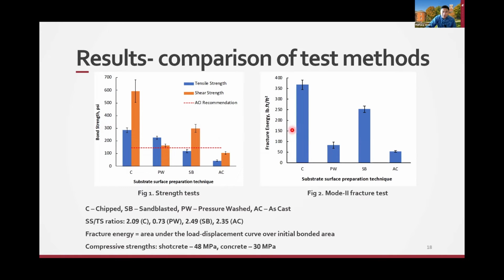In terms of the butterfly test method, which measures the fracture energy, because you do place the notch before the test, it follows the pattern of the shear. As you see, the chipped method surface preparation gives you the highest fracture energy, followed by sandblasting, then pressure washing, and as cast. So it seems mode 2, which is also a shear test, makes sense. It follows the same pattern as the shear strength test.